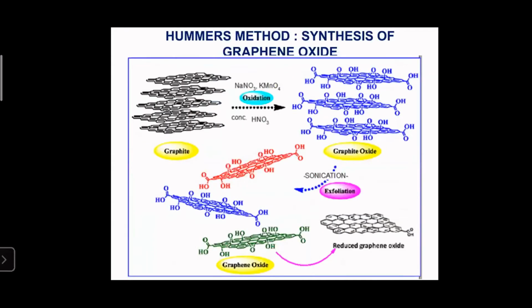Different oxidation methods are there for the production of graphite oxide from graphite, and the most common method is Hummers' method. We all know that graphite is a hydrophobic material, and initially for the production of graphite oxide, graphite is subjected to drastic oxidizing conditions using KMnO4, concentrated nitric acid, concentrated sulfuric acid, NaNO3, etc. As a result, graphite oxide is produced. Graphite oxide contains various functionalities such as epoxy, hydroxy, carbonyl, carboxyl, etc. As a result, the layer distance of graphite is enhanced. In addition, the material can incorporate polar solvents and it becomes hydrophilic in nature. And by ultrasonication, these graphite oxide layers are separated to form graphene oxide.